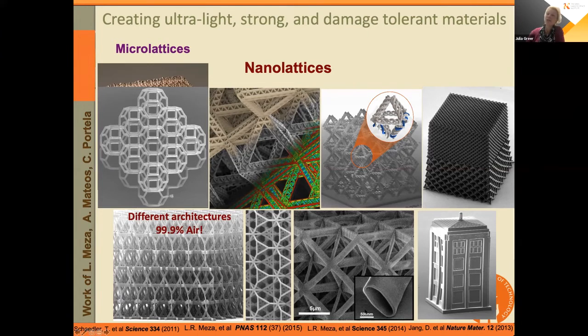And when you look into this image of a zoomed-in cross-section of a beam, you can see that they're hollow. And the wall thickness here can be on the order of some nanometers, maybe 5 nanometers or so. Now, when you look at this material as a whole, it's easy to see that it embodies every length scale from some nanometers to hundreds of nanometers and then to microns and hundreds of microns and now millimeters and centimeters.